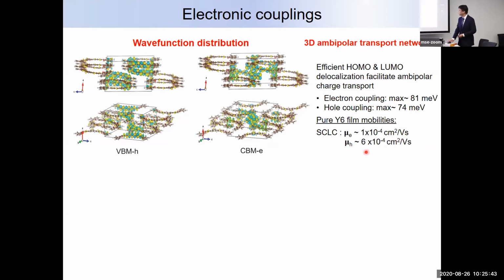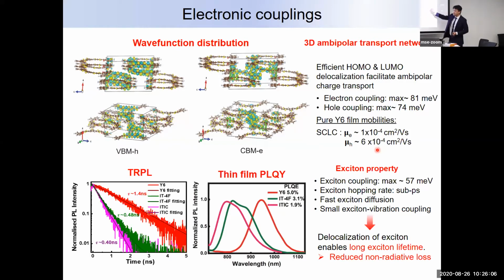And we also measured the space charge limited current for this Y6 pure film. So we observe that both electrons and holes can transport within this thin film. And the hole transporting property is even a little bit higher than the electron transporting property. And we further tried to look at the exciton properties. We can also calculate the exciton coupling energy, and it's also reasonably high. What does it mean? It means that the exciton can diffuse relatively fast.